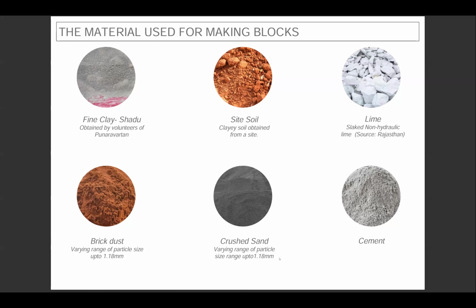Brick dust was a major material that we did use. I'm not calling this surki because, as I've learned from Yogananda sir, Pramod sir and Sudhakar sir, we have been collaborating with them on multiple projects and have learned a lot from them. I learned the difference between surki, which is essentially under 90 microns. If the brick dust is sieved, it is called surki, which is 100% pozzolanic material. But on site, when we are actually working, it's next to impossible to sieve brick dust under 90 microns. So we are using brick dust, which is essentially a combination of surki, which is the particles under 90 micron, and the remaining particles could be considered as aggregate for the soil as well. Then we did use some crushed sand and some cement for the stabilized mixes also.